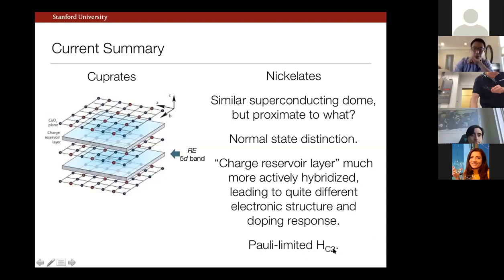And finally, I showed you a rather surprising, unexpected observation for us: that the upper critical field is quite isotropic and seems to be governed by a Pauli-limited scale in terms of Hc2. As far as I am aware, I don't know of any oxide systems where that is the case. The few cases I'm aware of are heavy fermions, so that seems also rather unusual and much more to be studied, especially with respect to this low temperature upturn.